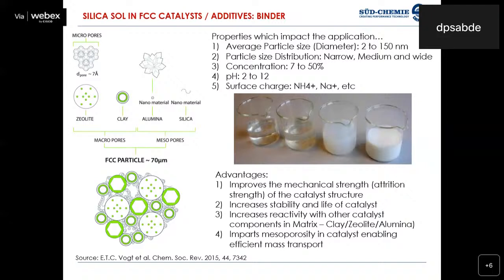range. So the most important thing, as it is a fluidized application, is the density and the particle size of the FCC particles. These FCC additives are spray dried products, wherein the average particle size is somewhere around 70 microns. What is important for the application is that it should have better binding power, so that there is lower breakdown and the stability of the catalyst remains intact.